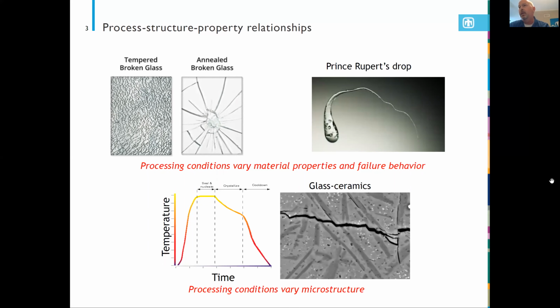The result is that the exterior of the molten bulb actually solidifies first, which puts the exterior surface in compression while the interior will be in tension. And as a result, it can withstand some significantly high compressive forces. So a lot of these videos show people hitting the bulb with a hammer and it doesn't fracture. It's quite impressive. The one way that you can break this Rupert drop is to break the tail of it. It breaks relatively easily, but the result is that the entirety will fracture into near-powder-size remnants. So it's quite impressive that by changing the way we process this given material, we can ultimately affect its failure behavior.